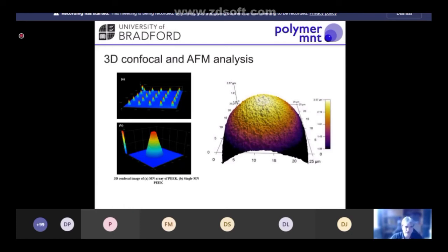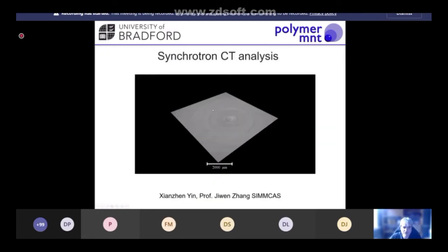So you can see here, this was captured using our Olympus LEXT 4000 3D scanning confocal microscope. And here we can see a nice consistency across the array. We can measure the heights and the tip radius of each needle on the array as well. If we want to investigate it with even more resolution, we can place one of these on an atomic force microscope, and we can get a very, very accurate measurement of the surface structure at the tip, and we can look at the tip geometry. But this is generally overkill, really. We don't need to measure with this level of accuracy for the majority of our microneedles.